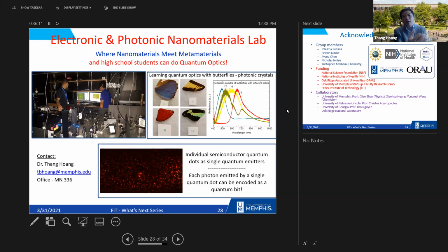Okay. So basically, when you generate an electron and hole pair in your active material, like a semiconductor, it takes some time for those charges to recombine into light. Before the charges recombine, the metal has already captured those charges. So that is typically what happens. In practice, we have to have a dielectric layer that separates the active material from the metal surface, so they are not in direct contact. Otherwise it looks like it quenches, not enhances. If you make it right, then it prevents the quenching and enhances more. If you don't, then it will be quenched more. That is engineering the structure. Yeah, very exciting.